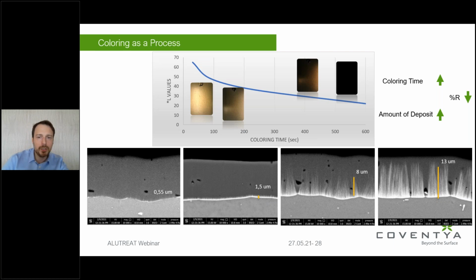As the time goes on, you see that the amount of precipitation in those pores is increasing, but it is not increasing at the same speed and efficiency. So, as you can see, the more time goes on, it's just like boiling water. Getting to black is more challenging than getting to dark brown. As a rule of thumb, increasing the coloring time, or even the voltage, not necessarily changes the shade itself, but more affects the amount of deposit, which in return makes the transparency of our oxide film less. Therefore, more light is absorbed and we get to black.